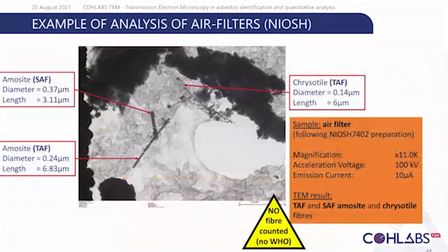An interesting example of an air filter. This filter was analyzed using the NIOSH method. As you can see on the picture, you can find three different fibers: two amosite fibers and one chrysotile fiber. And as you can see, they are all not part of the WHO characterization. So it's mainly short and thin asbestos fibers. For this example, if we had to give the results, we would say that we didn't find any fibers, because they were not part of the WHO characterization, and so they cannot be integrated to compare with the Australian